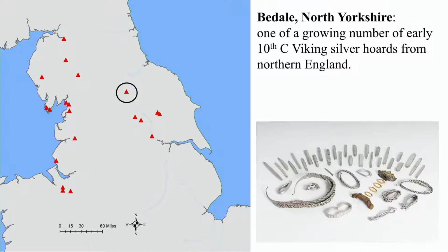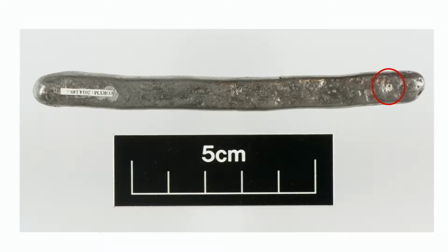Okay, so the last part here is about England. We analyzed this hoard with Jane Evans, who's here, at BGS. So she did the lead isotope analysis. This is a hoard in Yorkshire, beginning of the 10th century. And it has no coins in it, but it can be dated through stylistic features in some of the finds. So it's about 900. And we were able to actually take little samples for the lead isotope analysis. So it hardly broke through the surface, but that was still enough for the lead isotope analysis.